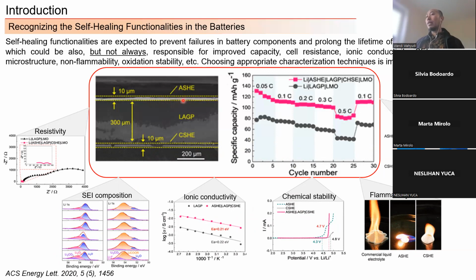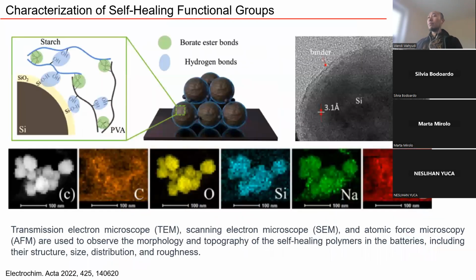interface layers between the anode and cathode before they have their solid state electrolytes, and they claim that by adding this interface layer, the cycle performance of the cell improves. But it is very important that we make sure the improvement in the cell performance is because of the self-healing functionalities that we introduce into the cell.